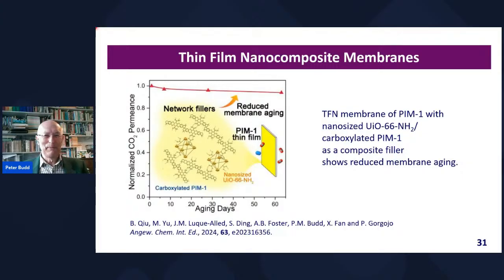Now, one thing about mixed matrix membranes is, again, most of the studies in the literature are on relatively thick films. And in reality, if you want to apply these things, you want to get to a very thin active layer. And so if you're going to have a thin layer, you also need a very small filler. So you have to think about controlling the particle size of the filler and get that down, ideally, to nanoscale. And so here's a bit of work from last year,